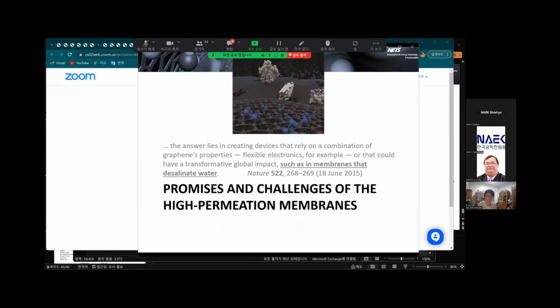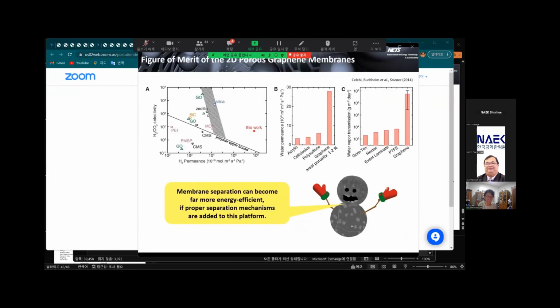Here is a brief discussion on the emerging high permeation membrane out of graphene, porous graphene. Figure of merit indicates that, thanks to ultimate gas permeation, the high permeation membrane will lie beyond the upper bound of current membrane materials. For ultrafiltration application, liquid permeation of the high permeation membrane exceeds that of polymer membranes, but just marginally. Surpassing PTFE-based membranes in water vapor transmission rate by many orders of magnitude, the high permeation membrane shows a potential for breathable fabric and breathable membrane.